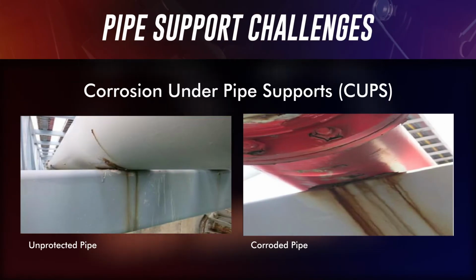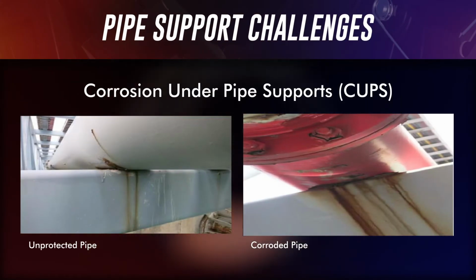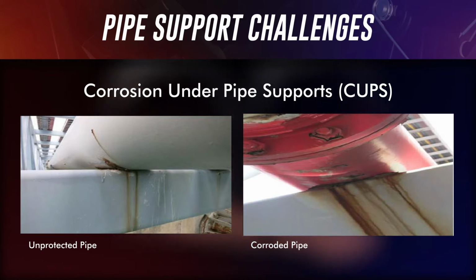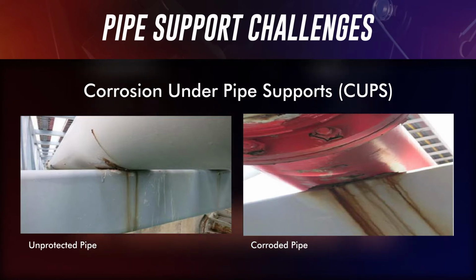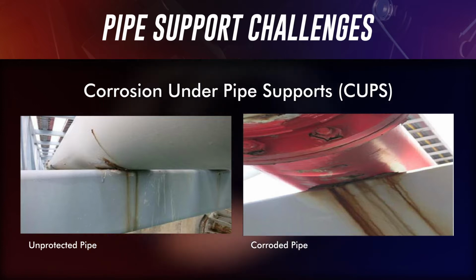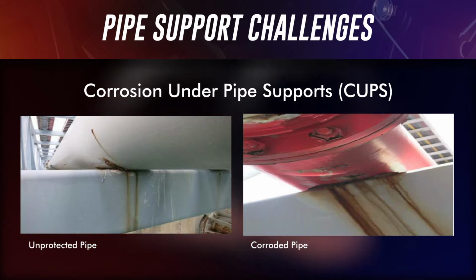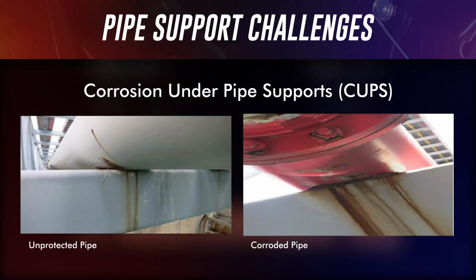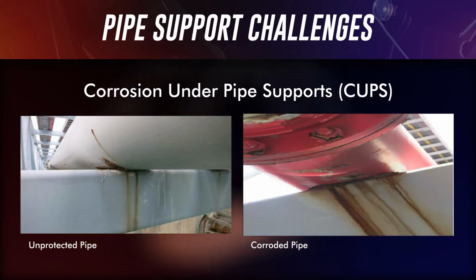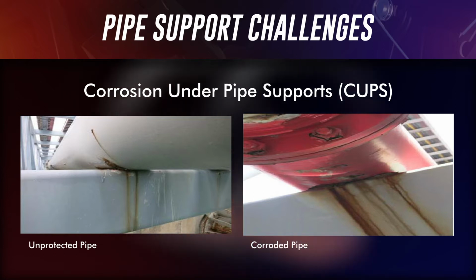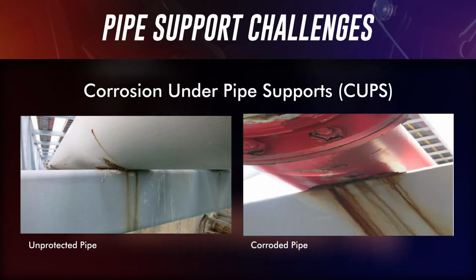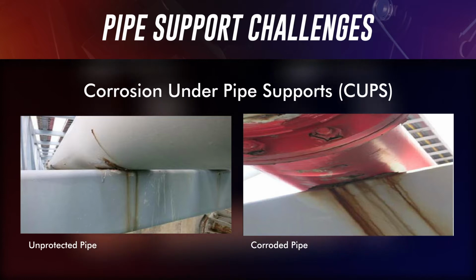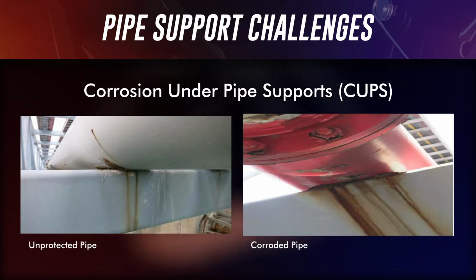When a pipe is resting on a support structure, it moves and vibrates due to rotating equipment, fluid flow, and the pipe's own expansion and contraction due to external and internal temperature fluctuations. Such movement causes friction between the pipe and its supporting structures, which erodes the pipe's protective paint coating over time. This, in turn, exposes the pipe's underlying surface to the elements, such as moisture and oxygen.